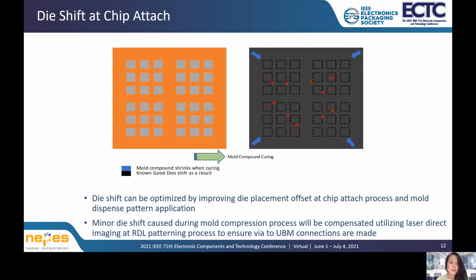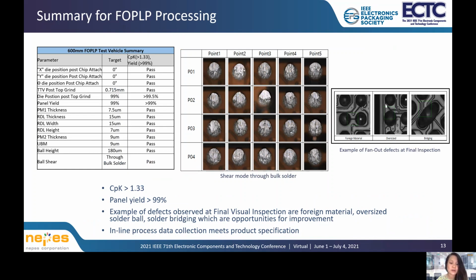Here's a summary of the process evaluation for the test vehicle. CPK is more than 1.33, panel processing yield above 99%, shear mode is through bulk solder, and defects observed at final automated visual inspection are similar to wafer level CSP defects in a sense that we have foreign material, oversized solder ball, or solder bridging. Defects are marked as rejects on the panel map.